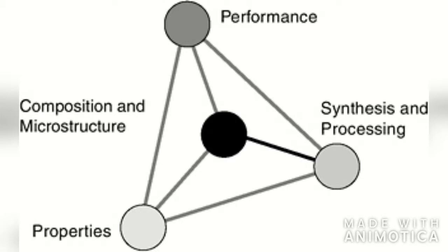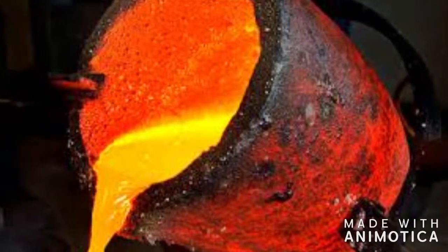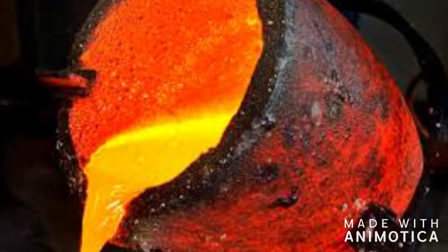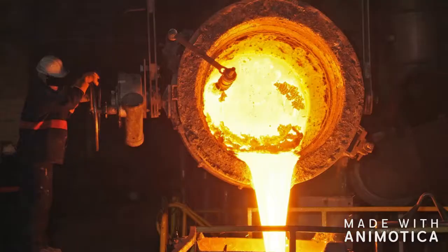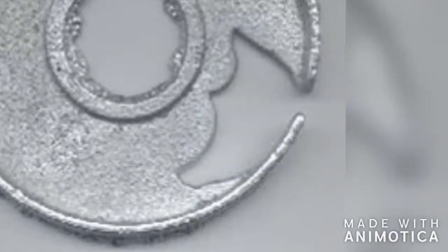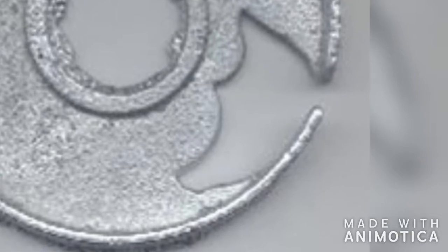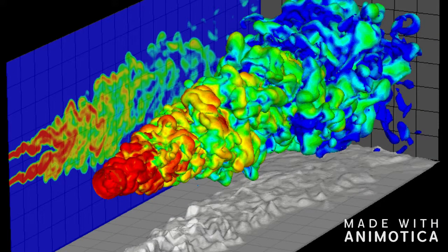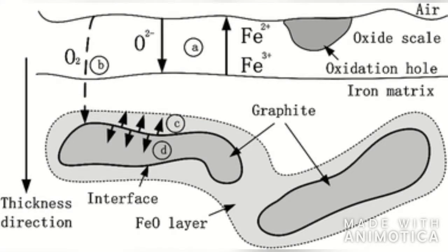There are a few processing factors that can affect the microstructure of the cast iron skillets. As mentioned before, the temperature of the molten metal at pouring is extremely important to producing quality cast iron skillets. However, in addition to the temperature, the rate at which the molten metal is poured can result in similar problems. Pouring the metal too slowly can result in the metal solidifying before it has reached all portions of the mold. Too quickly, and turbulence can be an issue. Turbulence is characterized by erratic variations in the magnitude and direction of the velocity throughout the fluid. This tends to accelerate the formation of metal oxides that become trapped during solidification and increase the rate at which the mold erodes. For these reasons, pouring the molten metal too quickly or too slowly should be avoided.